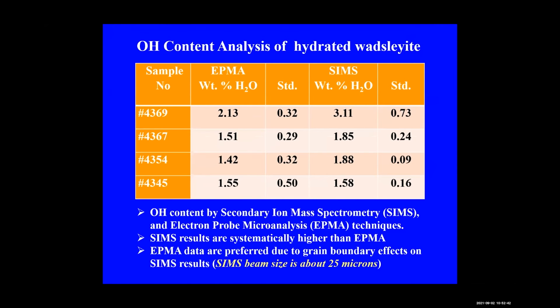So recently, we just completed analysis of the water content following 2 different techniques. We show here in this table that the water content was measured using the SIMS method and also by the EPMA microanalysis technique. But we see from the table that the water content from EPMA is consistently smaller than that measured by the SIMS technique. We associate the difference with the effect of grain boundaries on the SIMS technique, where the beam size is about 25 microns compared to 1 micron for the EPMA technique. So we are going to consistently use the water content measured by the EPMA technique for further analysis and discussion.